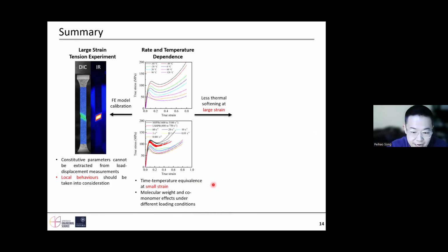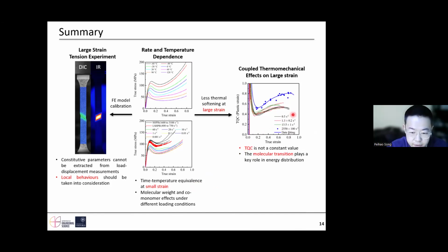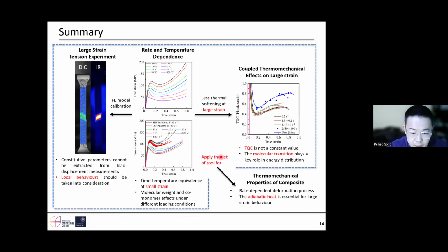To answer why there is less softening at large strain at high rate, I did a lot of temperature measurements. And the consequence is that the Taylor-Quinney coefficient is not a constant value. The molecular transition plays a very important role in energy distribution. After that, I applied the set of tool for thermomechanical characterization of composite material. The result shows that adiabatic heat is essential for the large strain behavior.